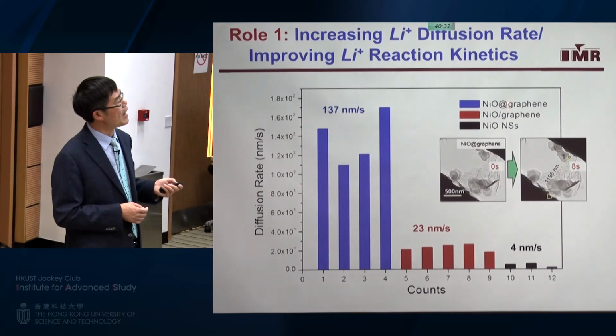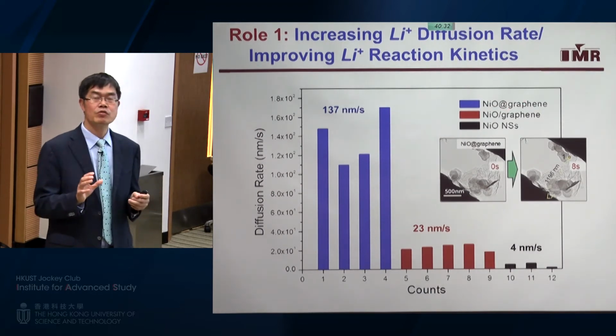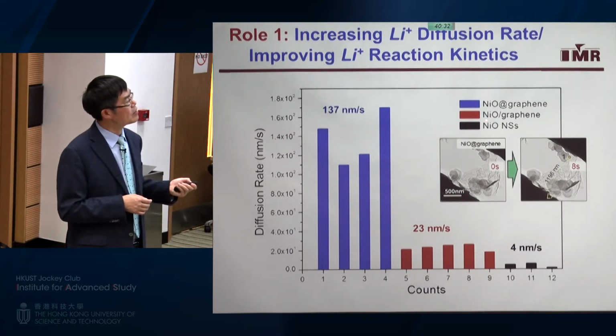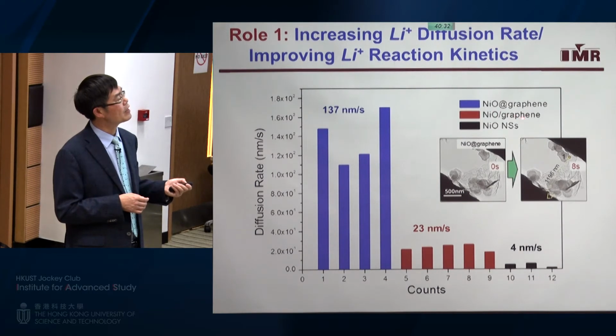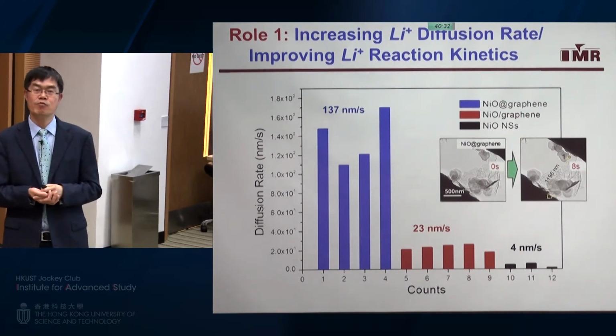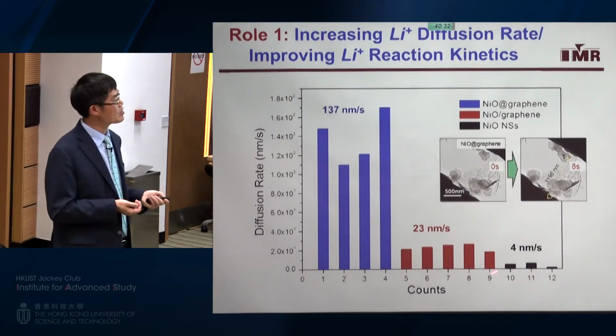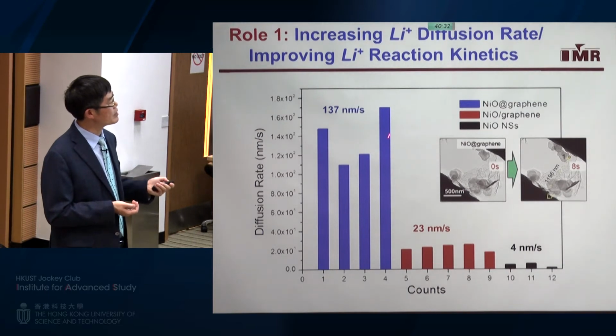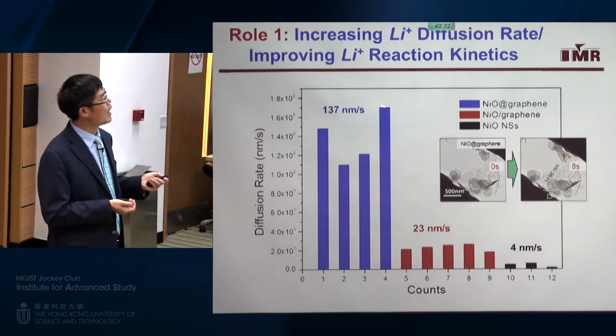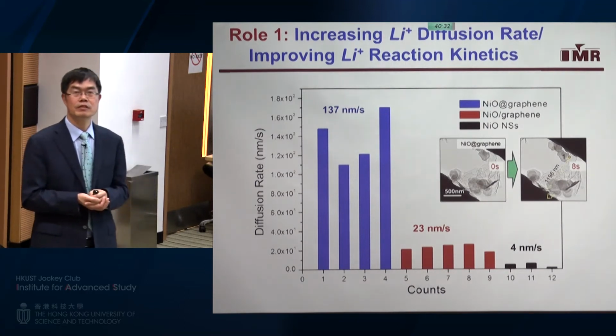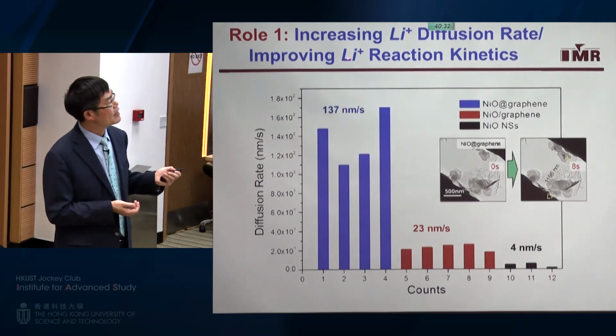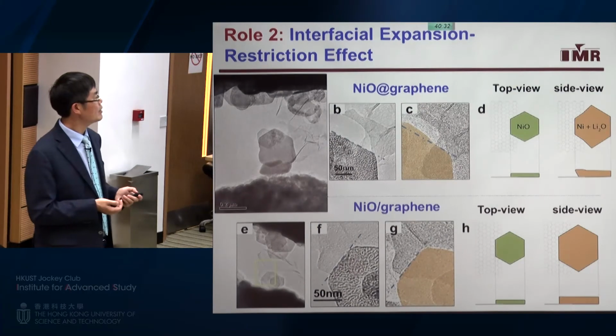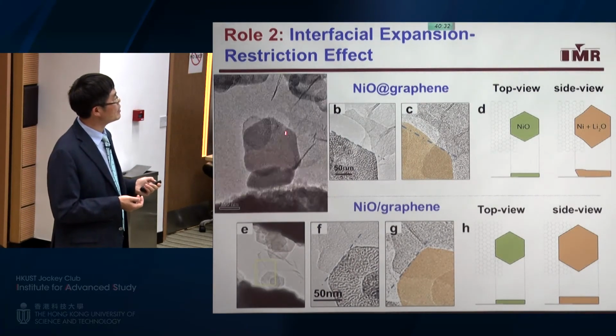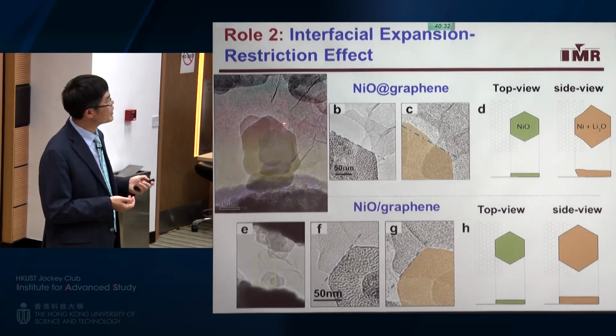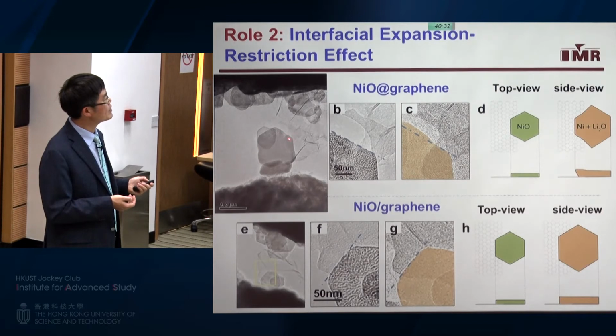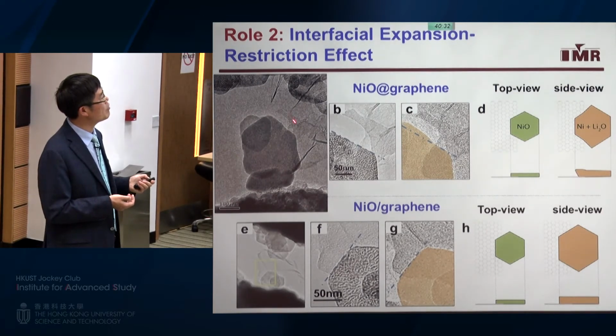You can say we have three model materials. This one is nickel oxide on graphene with very strong interaction. This one is nickel oxide and graphene by mechanical mixture with a weaker interaction, and then nickel oxide nanosheets. You can see, compared to these two materials, this strongly interacting hybrid material has a very high lithium diffusion rate, which means very high lithium reaction kinetics. This is a movie I can show you. Here, the graphene can prevent the volume expansion of nickel oxide.